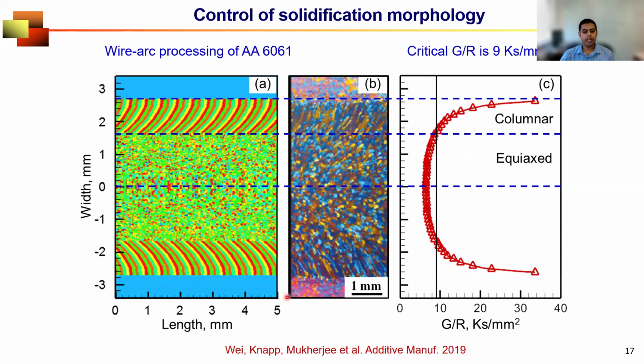Here we have used a model to calculate the G by R ratio for an aluminum alloy, a 6000 series aluminum alloy. The calculation is saying that this G by R ratio, which is the slope of the previous plot, varies spatially like this. We know for this material there is a critical G by R value that determines whether it will form columnar grains or equiaxed grains. For example, if the G by R ratio is more than 9, it will form columnar grains. If it is less than 9, it will form equiaxed grains.